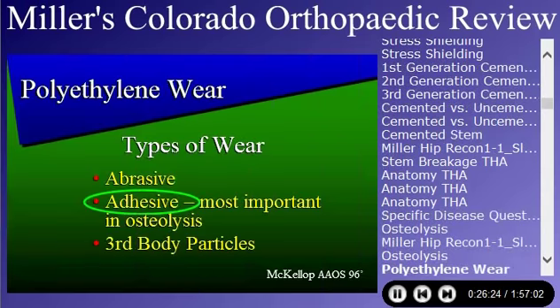The types of wear of polyethylene are abrasive wear. So if you have a rough head, you scratch on the polyethylene. That's a cheese grater effect. That's abrasive wear. The most important wear phenomenon is adhesive wear, which causes the main osteolytic problem. If you have poor technique and you have third body particles like cement debris or metal debris in there, you can get third body particles. But it is adhesive wear, which is the most important in terms of osteolysis.